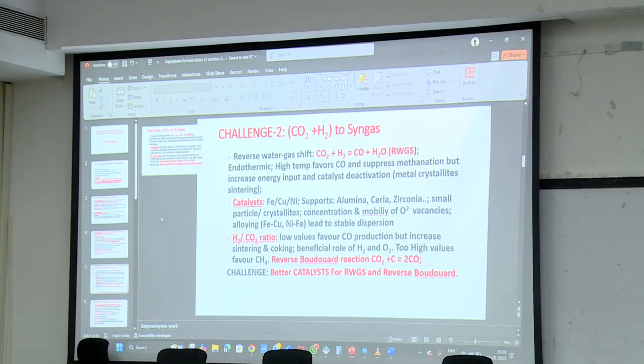And you can change the H2 to CO2 ratio. Low values favor CO production, but increase sintering and coking. Too high values, if you have a high H2 to CO2 ratio, you produce methane, not CO. And there is another reaction which comes into play here at low H2 ratio. That is the reverse Boudouard reaction. The Boudouard reaction is a disproportionation of two carbon monoxide to carbon and CO2. The challenge is to produce a better catalyst for RWGS and the reverse Boudouard.